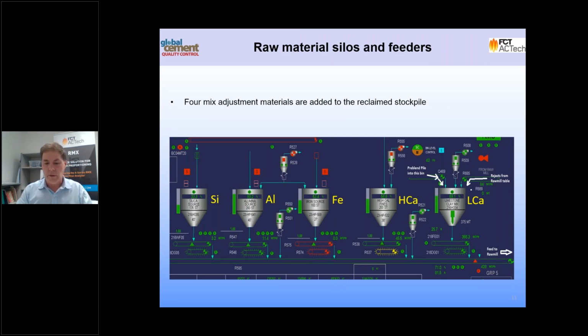So this is a screenshot from the control room showing the feed silos and their weigh feeders. And because of the operation of the weigh feeders, they're able to produce a very accurate proportioning control system. There's one difficulty with this system. For this particular plant, the material coming back from the pre-blend stockpile ends up in this bin here on the right. And the difficulty is that there's also the rejects from the raw mill table coming into here as well. So that means that they've not been analysed in any way prior to getting into this bin. So the proportioning system doesn't know about that material going in, and depending on the amount of that material, it can cause difficulty with getting the chemistry on target.